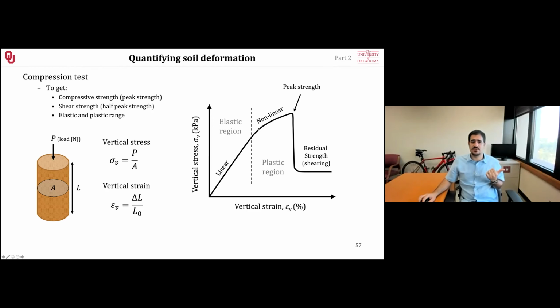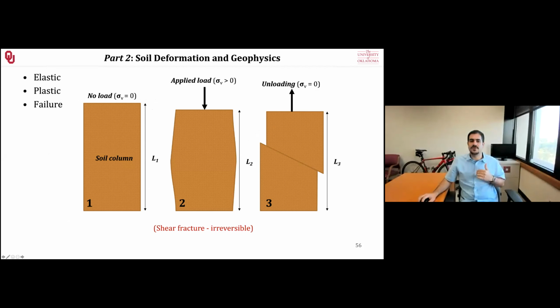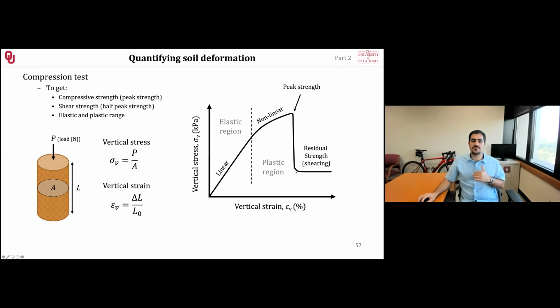But if you increase the load, we will get to a nonlinear part, which is the plastic form. Essentially, when the soil cannot handle more stress, it will fail on its fracture plane and start sliding on this. The only thing keeping the slide from being an instant thing is the friction in this plane as well. So that's why we see a sharp drop at the failure point. After that, all that remains is a residual strength. That's the only thing that's happening: the friction on the fracture plane.